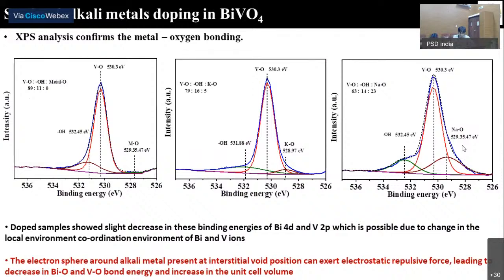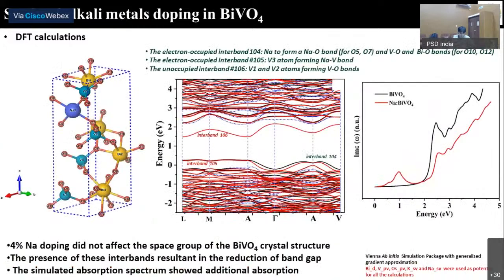So now we know that we have a bismuth vanadate system in which our dopants are going in the interstitial position. Now how it affects our band gap properties or absorption properties. For that we have done this DFT simulation. For that we have taken the unit cell of bismuth vanadate and we have placed sodium at different positions. I am showing only the lowest formation energy scheme. We put sodium in the different lattice positions and we calculated its formation energy, and we have taken based on the lowest formation energy.